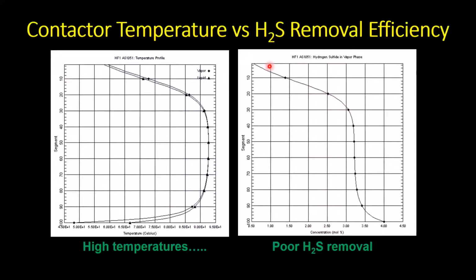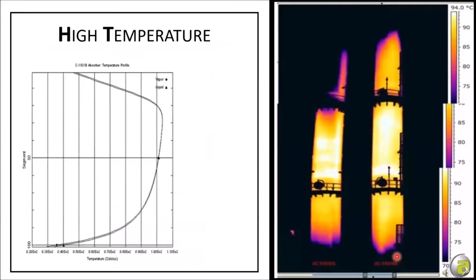The problem with this type of profile is we're not using 60% of the tower, which means we're not on spec at this point. This is 0.5% H2S in the treated gas. So that's clearly off spec. So temperature is a huge issue.